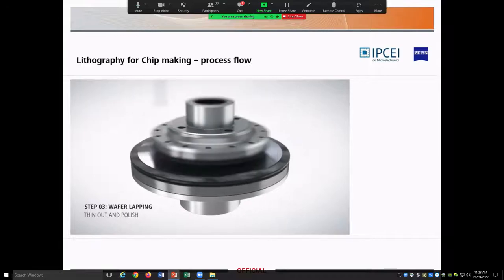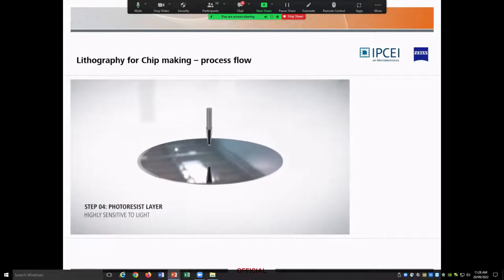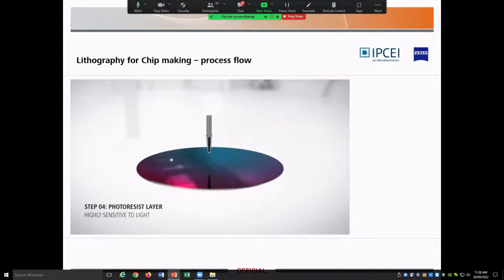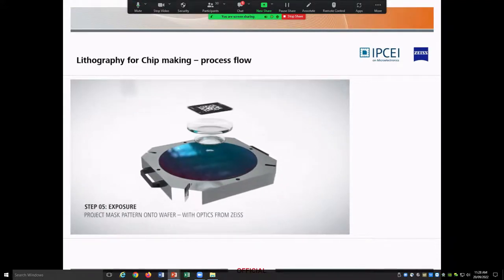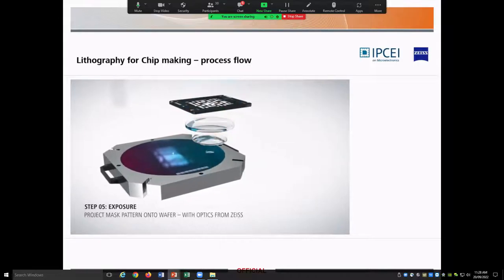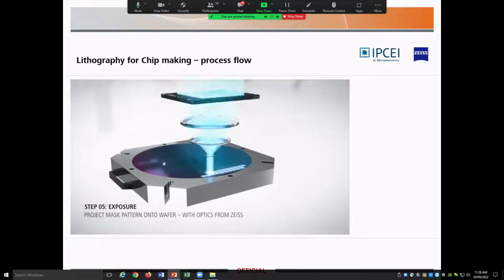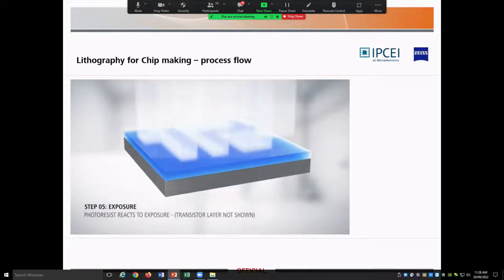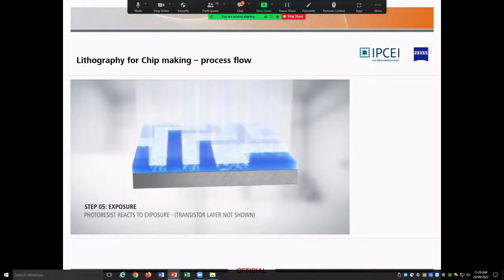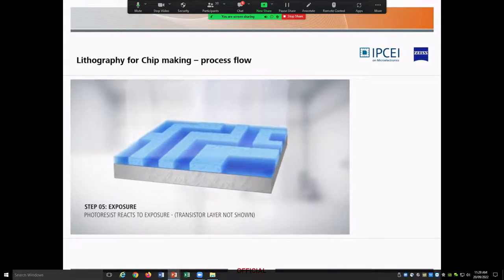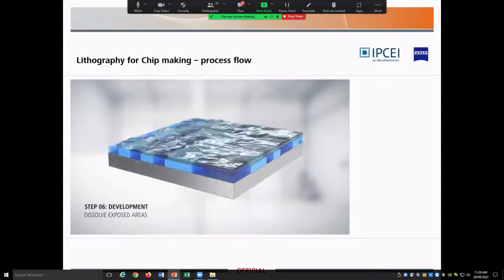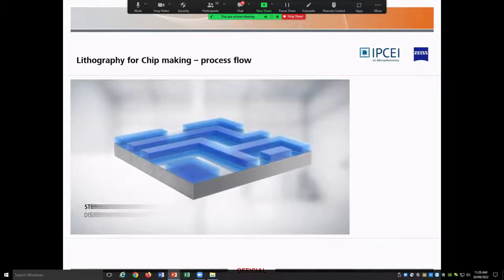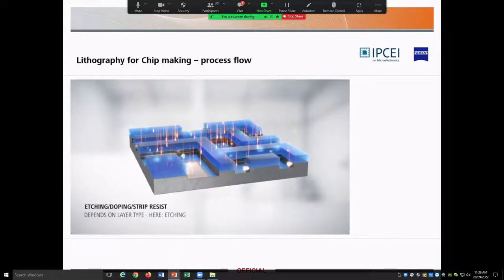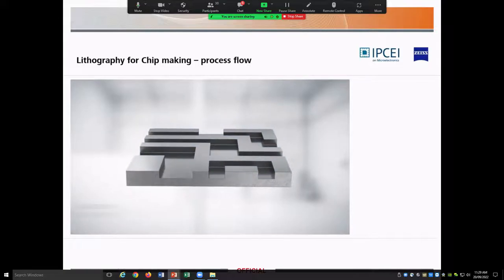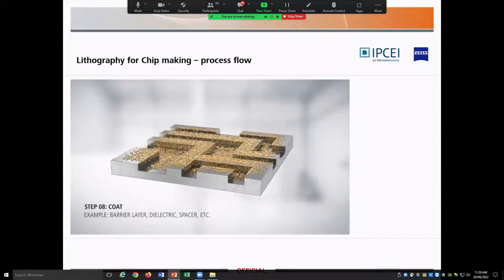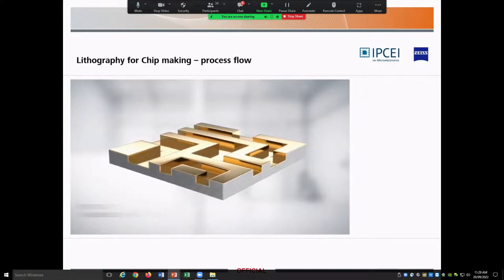So when we have the substrate ready, we coat it with photoresist. And then this photoresist-coated substrate will be exposed to UV light through optics and photomask. As I mentioned, some parts which were exposed undergo chemical changes and become soluble, and later these parts will be dissolved away in developing solution. And we have the photoresist pattern. We can do things to these open areas like etching, coatings, and this is, of course, just an example.